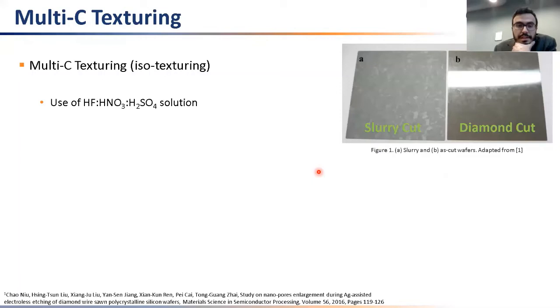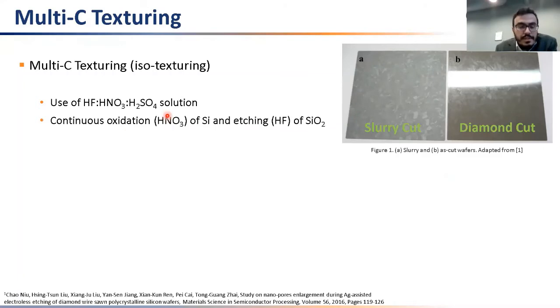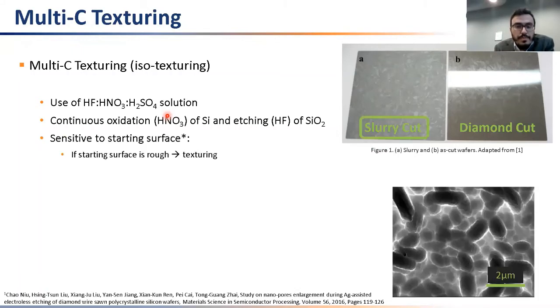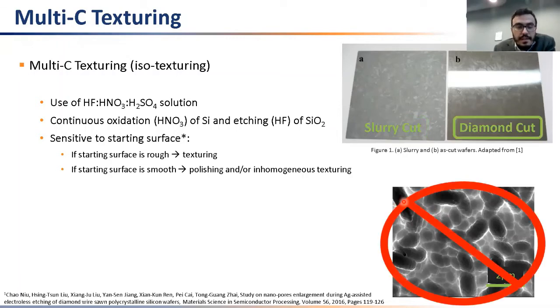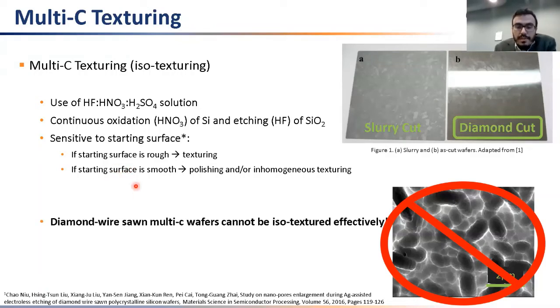So here, for multicrystalline texturing or isotexturing, we are using some acidic solutions which contain oxidizers and etch silicon, and it is sensitive to the starting surface. If the starting surface is rough, as in the case of slurry cutting surface, you can make isotexturing on your multicrystalline wafers. However, if the starting surface is smooth, as in diamond cut wafers, you cannot make this isotexturing on the surface. So diamond wire sawn multicrystalline wafers cannot be isotextured effectively, which is a problem of industry right now. And the solution of this is the nanotexturing, which is also applied industrially in crystalline silicon solar cells.